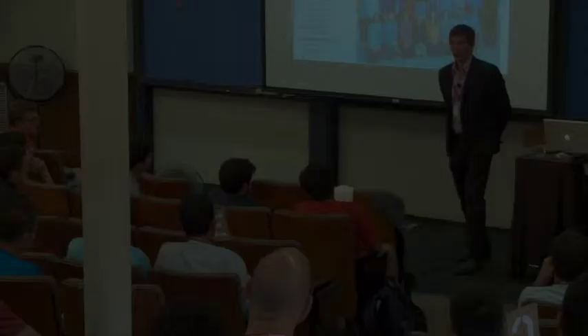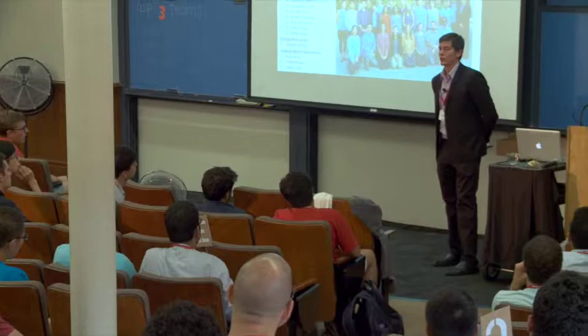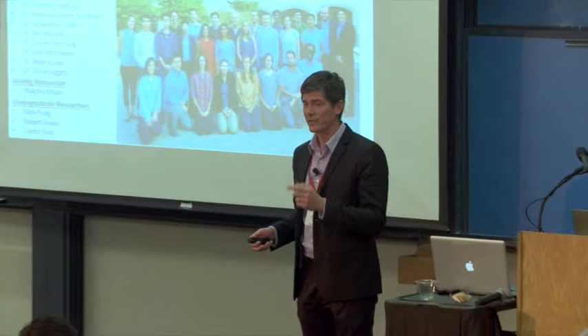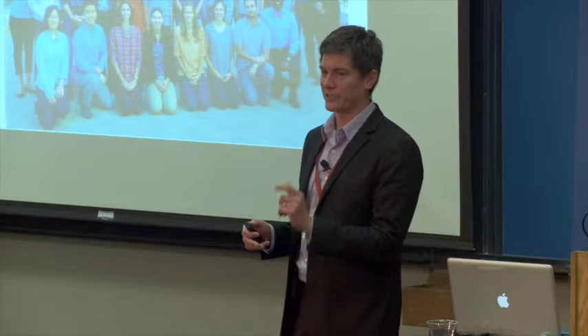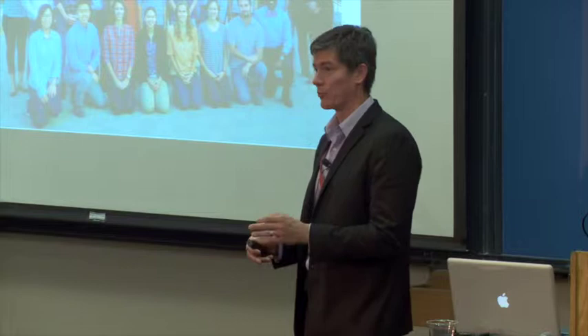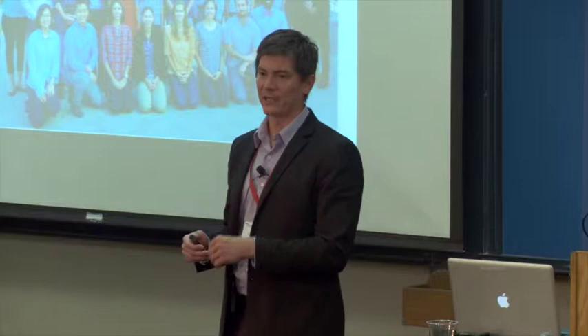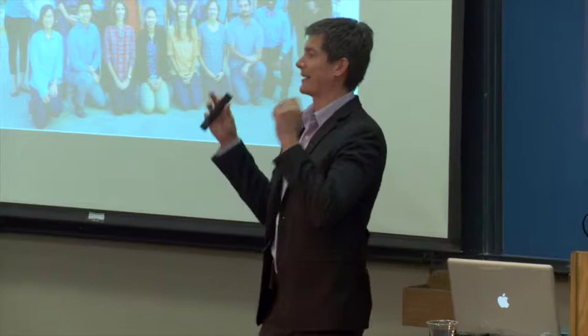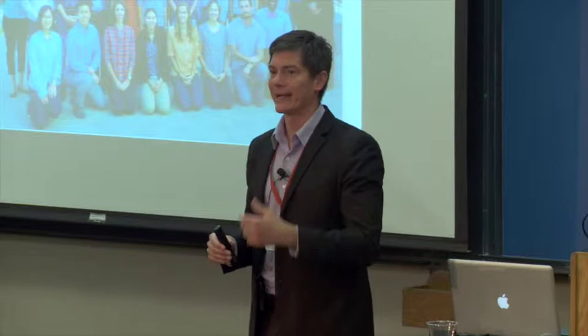Yes, sir. What kind of efficiency? So by the minimum thermodynamic efficiencies for hydrogen, we're probably around 60 to 70 to 80% efficient in those chemical transformations. Efficiency is always a tricky number because it's very related to your reaction rate. On the CO2, it's more like 40%. If you want to get really high reaction rates, that's part of the challenge. That's why with CO2, we're really far away from good catalysts. If you made perfect catalysts, just wonderfully, couldn't ask for anything more, then we would be in the 80 to 90% efficiency range. And I think once you're there, then you're good to go.